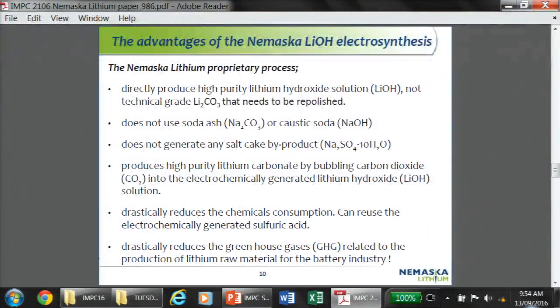And it's easy after that to produce lithium carbonate, because you can have customers that need both hydroxide and carbonate for different reasons. So you just need to bubble CO2 into your lithium hydroxide solution and you will precipitate lithium carbonate.